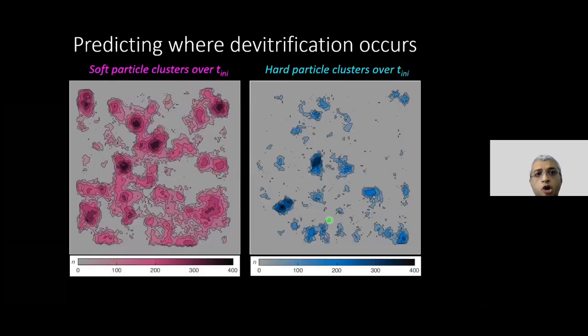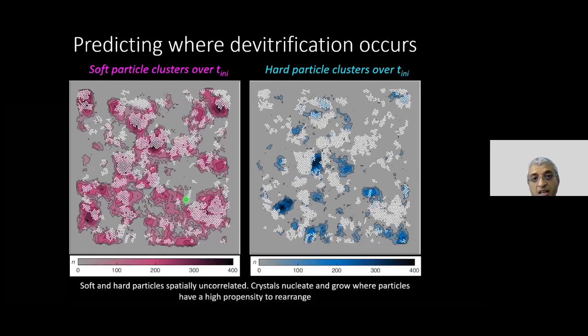Okay, so these are my soft particle clusters. t_ini is the time over which I didn't see any nucleation. These are my hard particle clusters. Of course, soft and hard particles do not overlap in space because these are locally different in their local structure. But then these are the crystals that appeared much later.